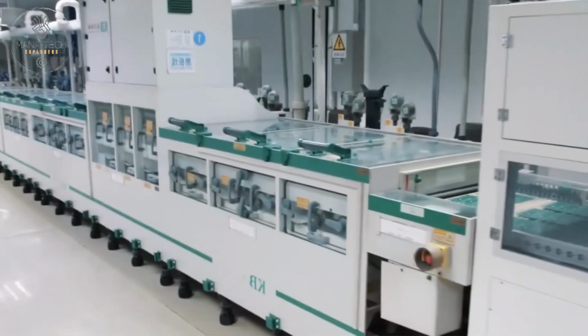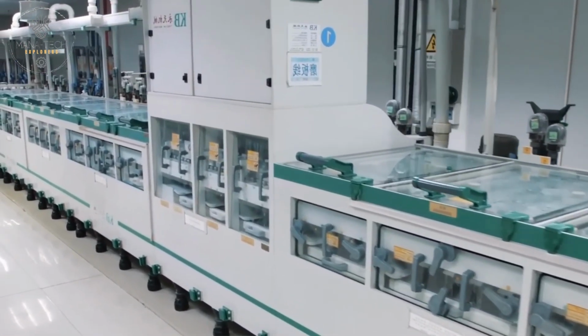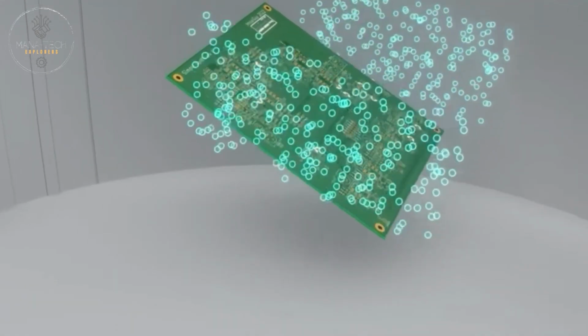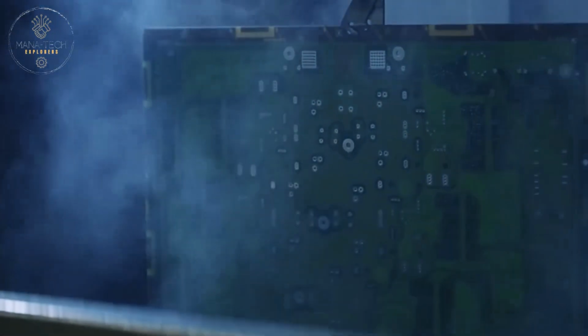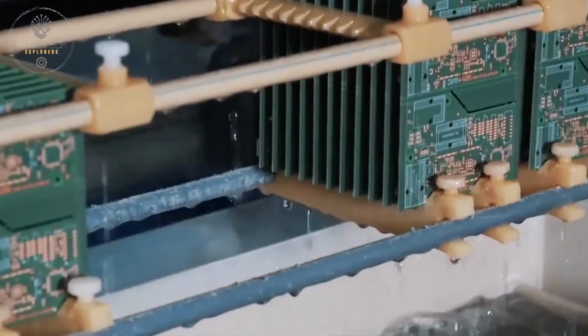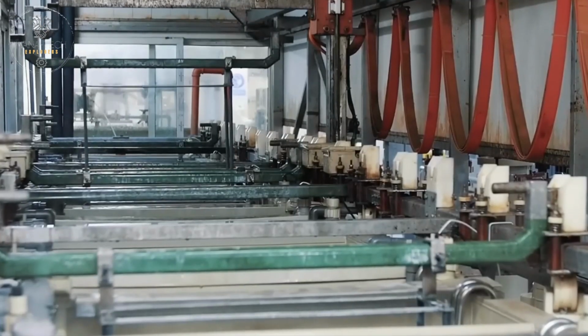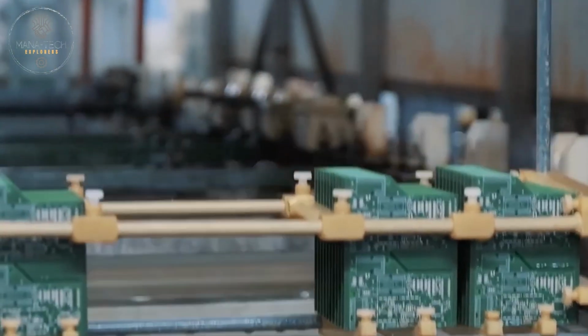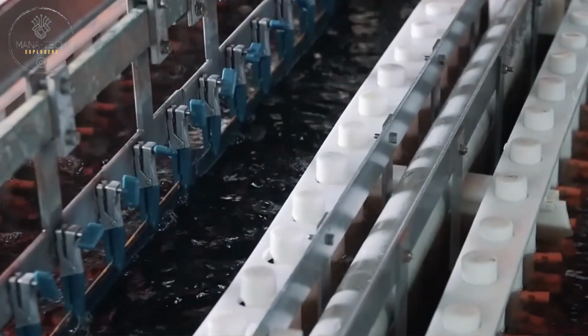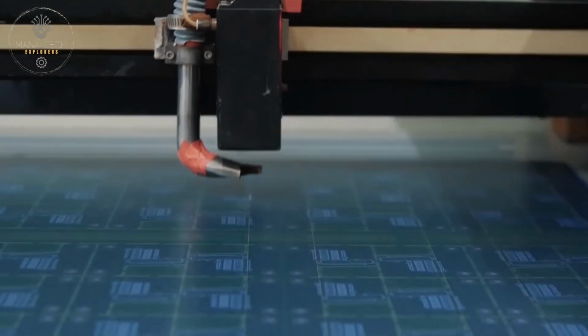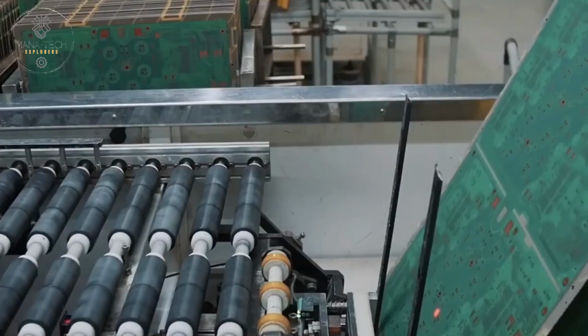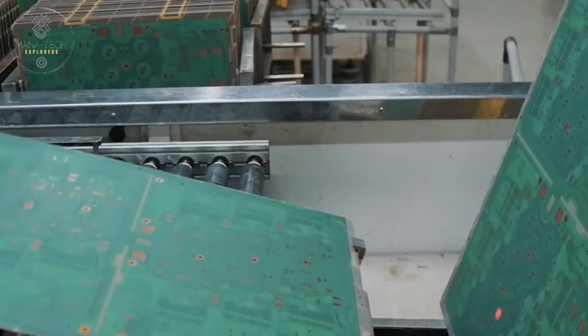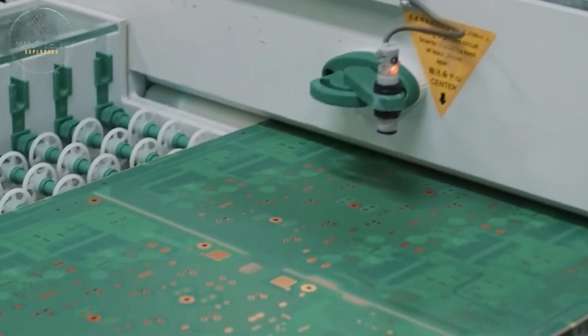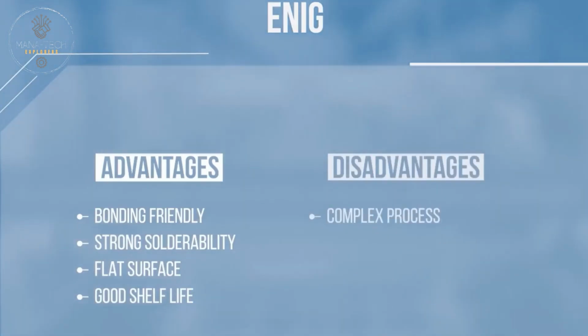Non-essential copper areas are often masked with protective tape to prevent excessive gold deposition. The circuit boards then pass through a series of chemical processing baths. First, a thin electroless nickel layer, approximately 3 to 6 micrometers thick, is deposited to improve adhesion, mechanical strength, and durability. Next, an ultra-thin immersion gold layer, with a minimum thickness of 0.05 micrometers, is applied through an immersion process. This gold layer protects the nickel surface and provides a stable, reliable soldering interface. As a result, the PCB surface achieves excellent flatness, strong solderability, and extended shelf life. However, ENIG also has notable drawbacks, including a more complex process flow and significantly higher production costs.